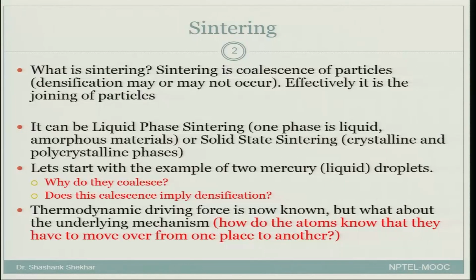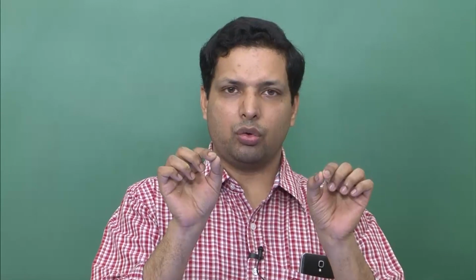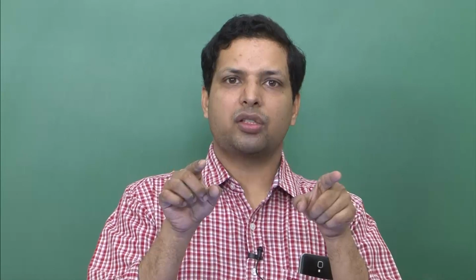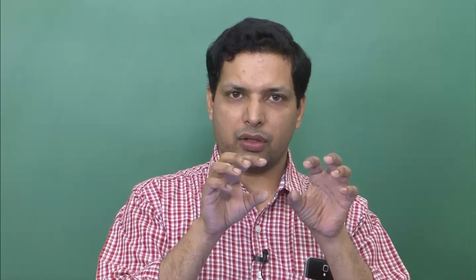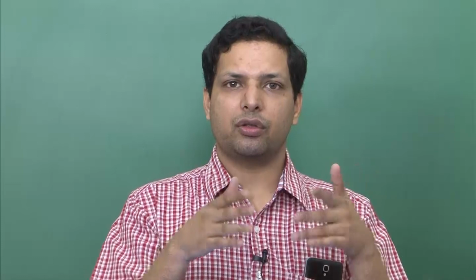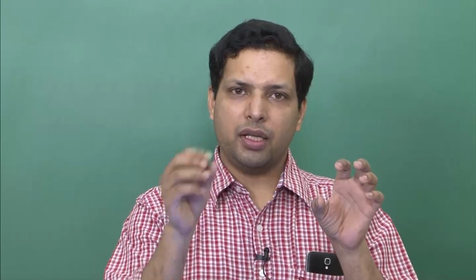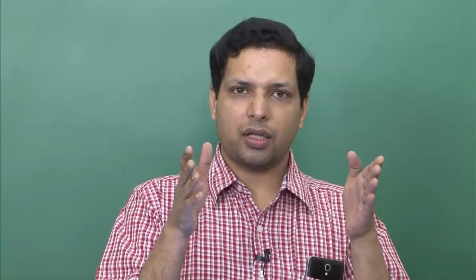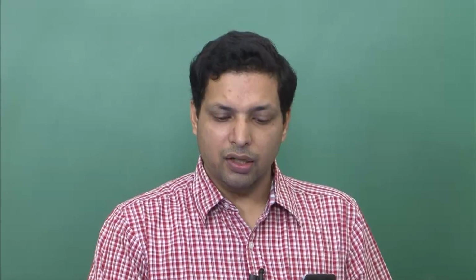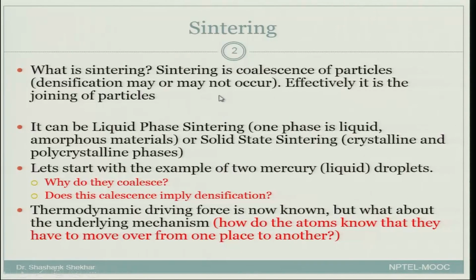We will see, for example, if you have two particles in very close contact with each other, the mass can flow and get deposited over here, but the center of gravity of the two particles may remain constant and not change. In that case, densification is not occurring, and the overall shape of the particle has changed because of the sintering process, but the particle center to center distance has not reduced. So we will say that densification has not occurred. On the other hand, if mass moves from the inside of the material to the neck region and finally reduces the center to center distance, then we will say densification has also occurred. So remember, sintering is coalescence of particles. Densification may or may not occur. Effectively, it is the joining of particles.